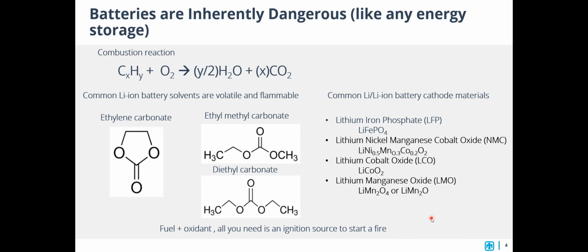And then if we look at the common cathode materials for a lithium ion or lithium battery, we see a lot of metal oxides or oxygen containing species. And when these decompose, they can form oxygen. So essentially a battery self-contains everything you need to start a fire, as long as there's enough heat or an ignition source, which is quite common when you're dealing with electronics or different kinds of mechanical failures.